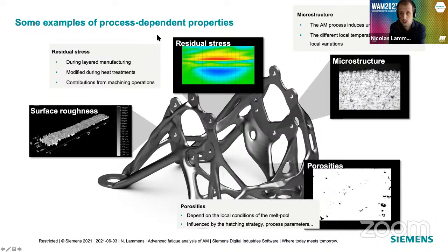So it's important to know these. Another one is microstructure. The previous talk has illustrated quite well how microstructure can affect performance. And here also the additive process gives us an additional challenge because you get a unique microstructure just because of the heating and cooling rates. And depending on the geometry of your component, the microstructure is not uniform throughout the part. If you have thin walled sections or you have bulk parts, or you have parts that are very close to another part in the build and see a lot of heat from that, they can all affect the microstructure.